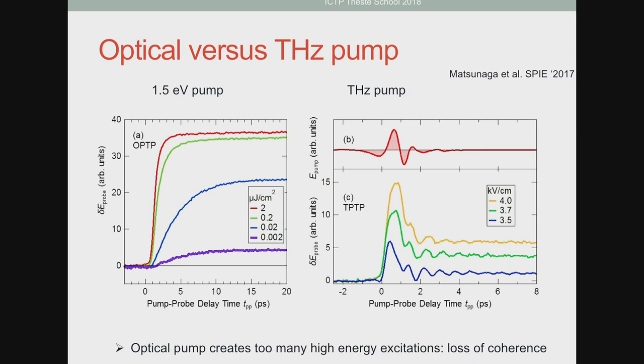Okay, so just to show you, it's interesting to compare the same measurements, but now you don't pump with low energy pulses, close to delta, but you pump at a much higher frequency. So you use a visible pulse, for example. Now, if you do that, this is the measurement here on the left, what you see is a large signal, but there are absolutely no oscillations.